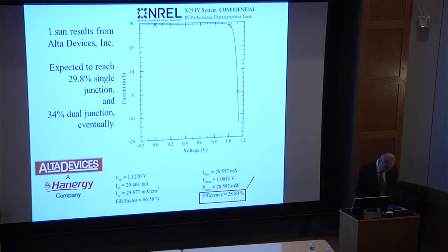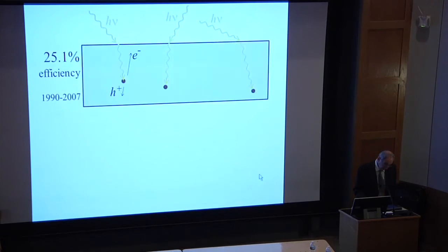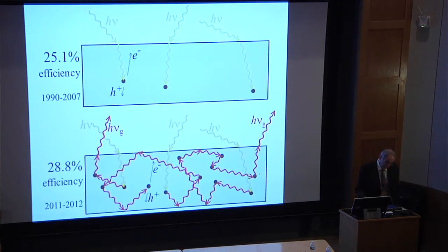It is still the record. It's about 3 years old now, and it's quite a respectable cell. And as I mentioned, it broke the earlier records by almost 4%. So it's because it had this new physics in it. And I think I mentioned the story is that what happened is that they started getting amazing voltages as soon as they peeled the film off.